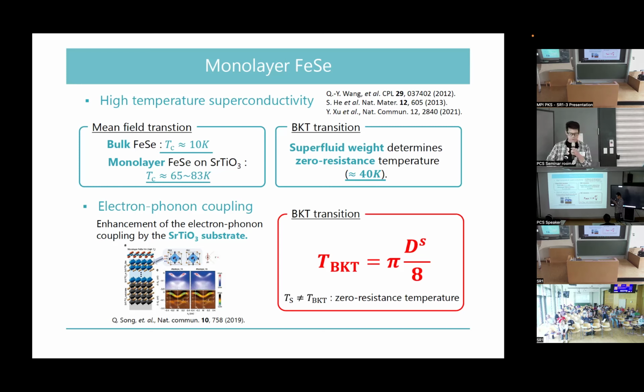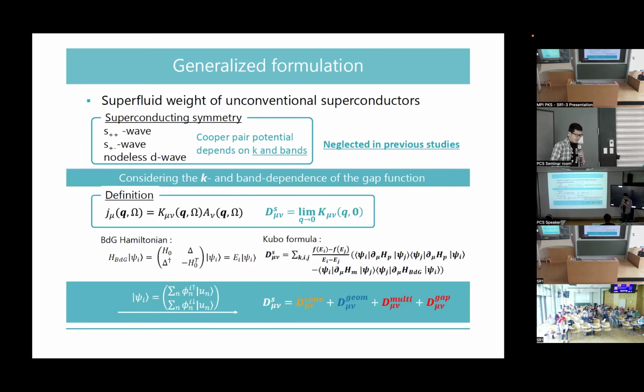And it is reasonable to consider that this transition temperature is related to the superfluid weight, because the BKT transition temperature is determined by the so-called Nelson-Kosterlitz relation, as shown here. So to evaluate the contribution of quantum metric to the superfluid weight and transition temperature in monolayer iron selenide, we derived a generalized formula of the superfluid weight in unconventional superconductors. Because the momentum dependence and band dependence were neglected in the previous theories, we extended the formula to take into account the unconventional properties. And we found that the superfluid weight can be decomposed into four terms like this, and two of them have geometric contributions.